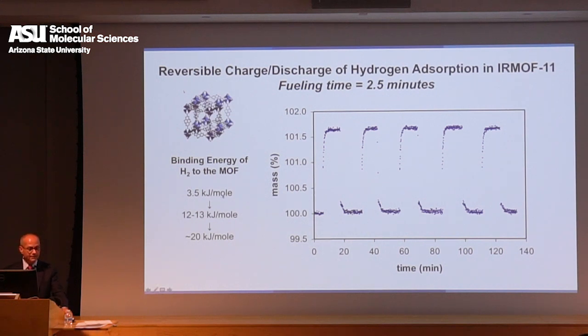This is for MOF-5. So we have been able, through tinkering with the MOF, to get it to be stronger and store around 2 to 2.5 weight percent of hydrogen. We need to get to 20 kilojoules per mole to be able to store enough to make it interesting for automobile fueling. So 20 kilojoules per mole, that's the strength of a hydrogen bond, okay? But you can't go stronger because then you have to put in heat to take it out. You can't go weaker because then you can't store enough hydrogen.